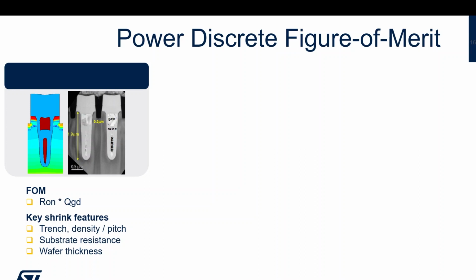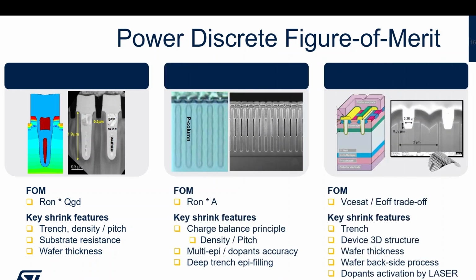Let me say a few things about the manufacturing of silicon power devices. Over the years, the structure has changed a lot. Just to give you an example, the surface is here. Most modern power devices have a trench structure in which the gate oxide is on the wall of a trench, so a really three-dimensional structure in which you have a lot of etching, a lot of litho, a lot of things to control. And also in the case of very high voltage devices, you have this three-dimensional structure. This is fully crystalline, but you have P-type doping going up to 40 micron for a 650 volt device, immersed in N-type, in order to have a 2D electric field and get better on resistance, better performance.